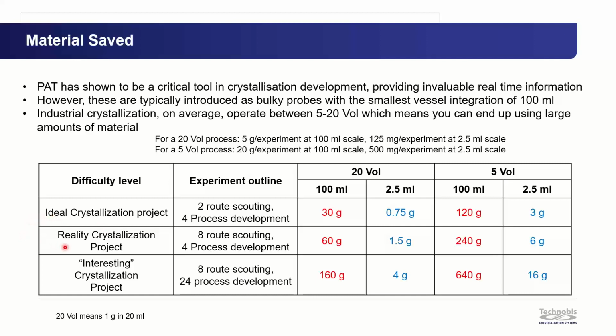If you start having more problems, so a realistic crystallization project where it has secondary forms, you need to do anti-solvent, so screening for that, addition rates. This can then start to ramp up even more to 60 to 240 grams. And what became known by many people as an interesting crystallization project is something that gums, oils, has multiple polymorphs, forms needles that stick together and block filters and stirrers. And this can take a lot of material, so anywhere between 160 grams to 640 grams of material at the 100 milliliter scale. However, by being able to operate at 2.5 milliliters, you can reduce this down from 4 grams to 16 grams to conduct all these experiments which you would need to understand maybe a complex crystallization process.